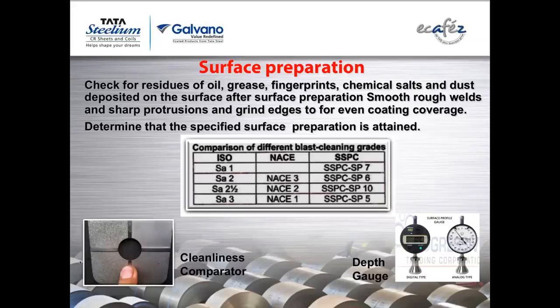So basically, there are some international standards. At the center, you'll find there's a small table. You can get them on the internet. There is one ISO, earlier we used to call it the Swedish standard, where we call it SA1, SA2, SA2 and a half, SA3. Equivalent SSPC grades are also given. Basically, SA3 we call white metal blast. That is, if I cut one HR sheet with a hacksaw, the inside metal that I see is what we call white metal. So for SA3, I am removing so much of the layer of impurities from the surface so that white metal is seen.